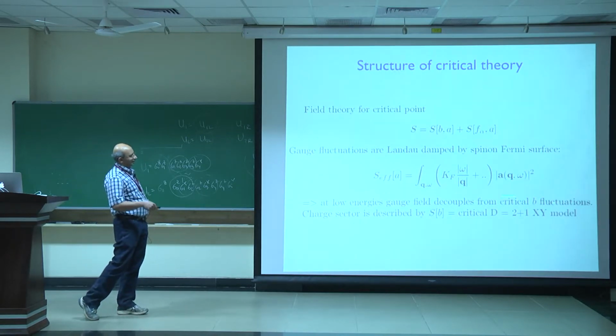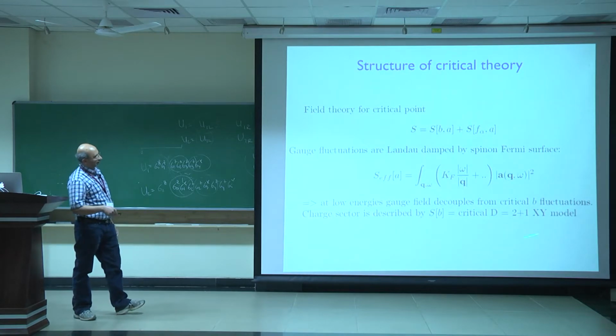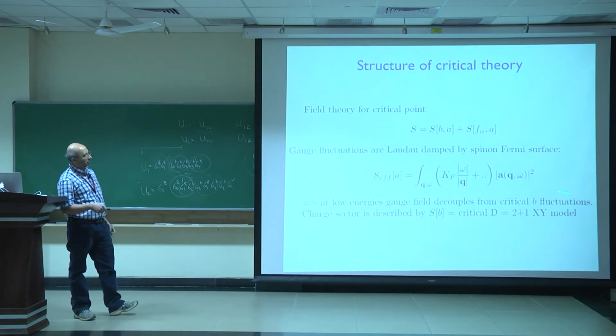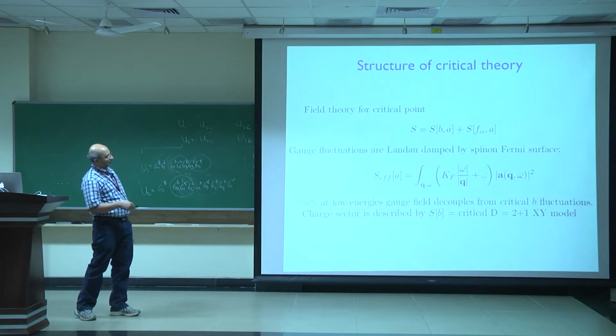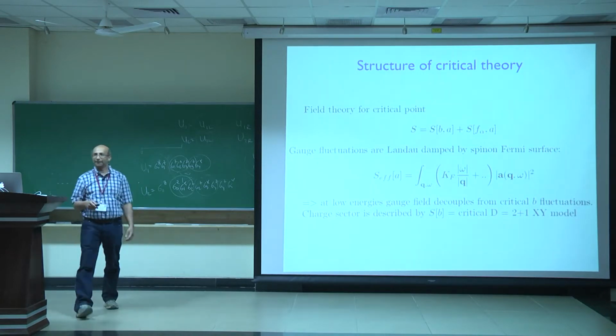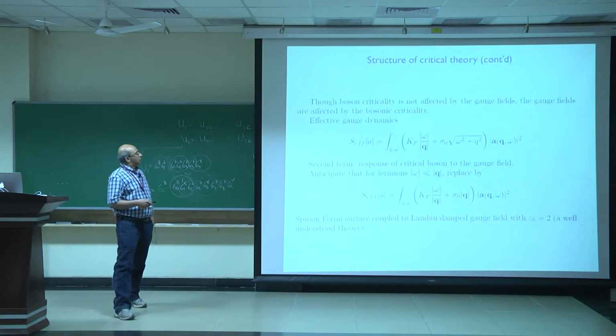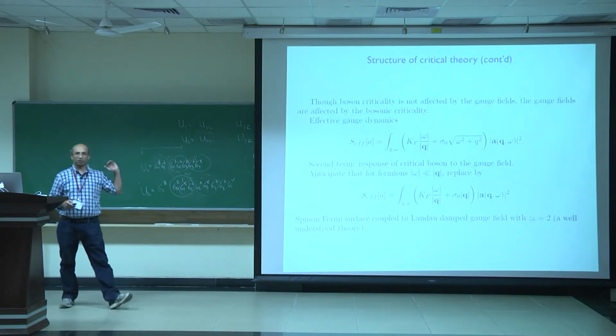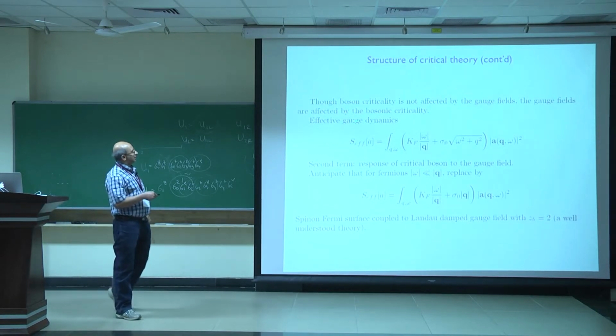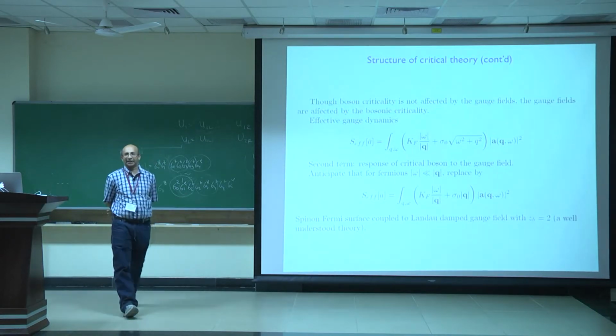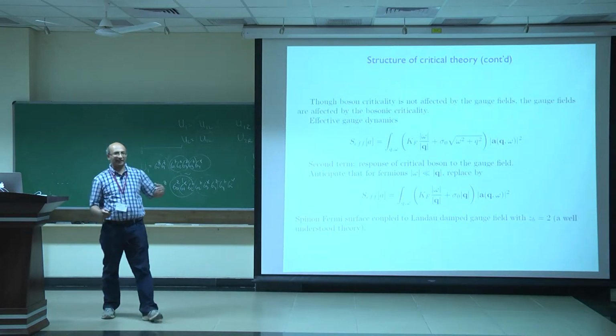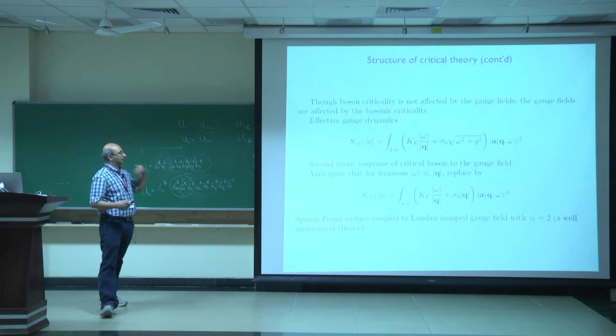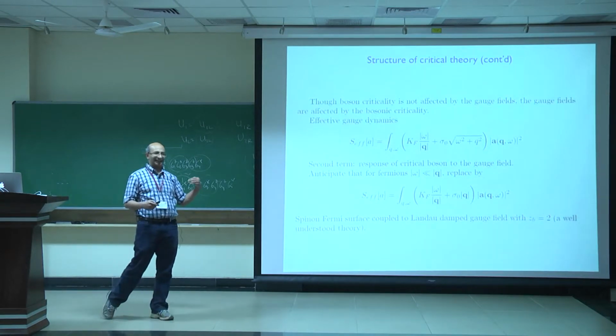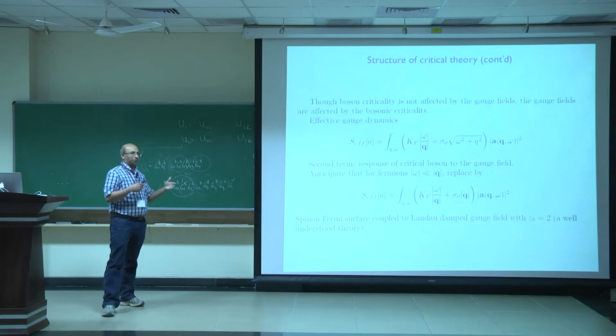Now, this model, since it's relativistic, its important critical fluctuations occur at frequencies of order the momentum. On that scale, this looks like a mass term, and this is the rough argument, and therefore, these gauge fluctuations don't affect the bosonic criticality. Okay? But the weird thing, so that's the first observation. The second observation is that even though the bosonic criticality is not affected by the gauge fields, the gauge fields themselves are affected by the bosonic criticality. Right? It's a one-way effect.